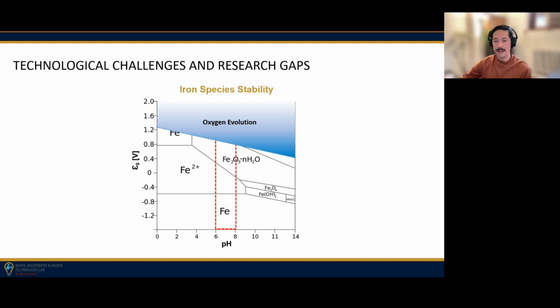So if we think first about our ferrate example, our iron example, and we think about the pHs that we would have for drinking water, which would be in the circumneutral range, so let's say anywhere between 6 and 8. And we look at where ferrate predominates in an electrochemical system, we see that we have to increase our potential quite high. So kind of in the 1.2 volts to 2 volts is where our ferrate is stable. The problem with electrochemistry is that the thing that is surrounding your electrode predominantly is water, right? Water is all over our electrode surface, and water also likes to react with our electrodes. And water reacts to make oxygen. So we'll make hydroxide and oxygen. So any possibility of actually making ferrate is overpowered by oxygen using standard metal electrodes.